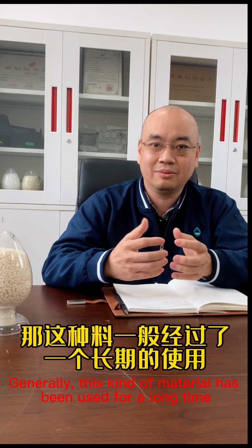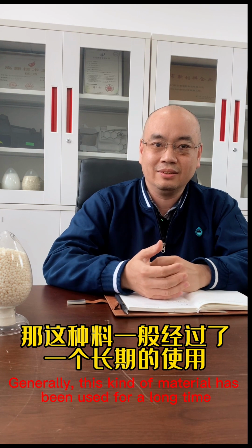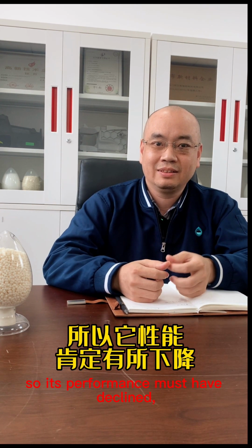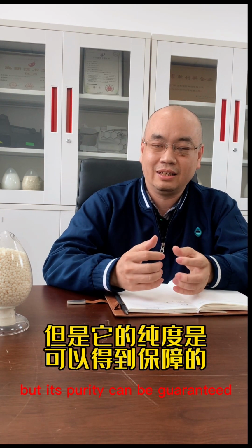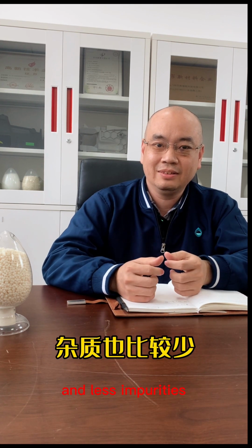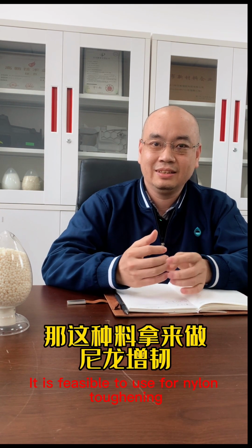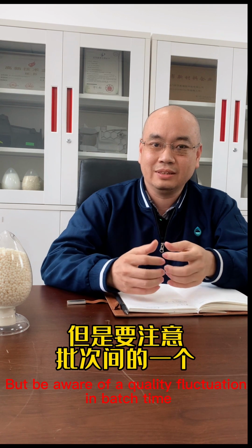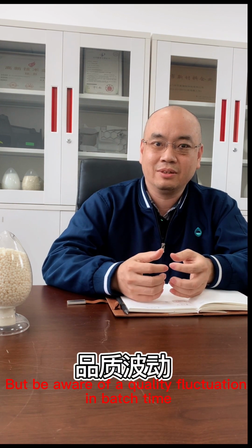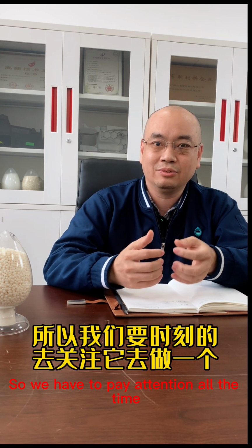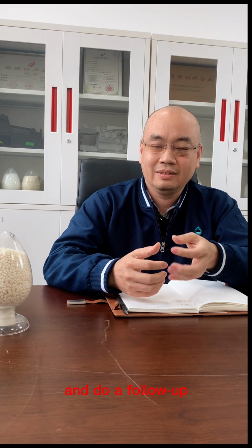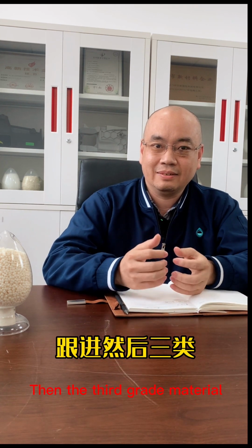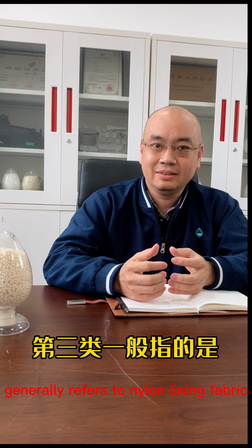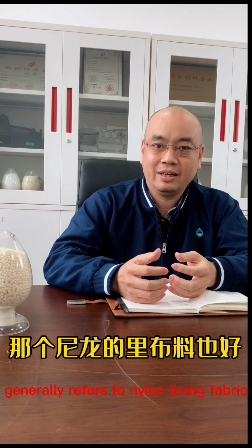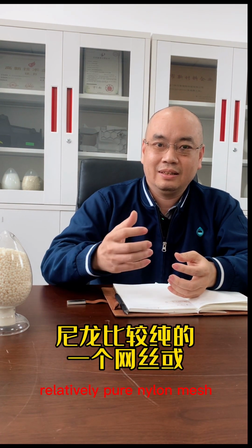Generally, this kind of material has been used for a long time, so its performance must have declined, but its purity can be guaranteed. With fewer impurities, it is feasible to use for nylon toughening. But be aware of quality fluctuation from batch to batch, so we have to pay attention all the time and do a follow-up. Then the third grade material generally refers to nylon lining fabric, relatively pure nylon mesh.